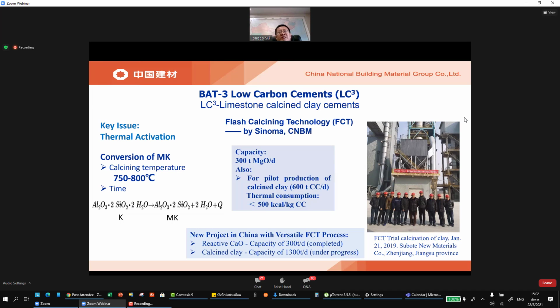And also the thermal consumption of the system is less than 500 kilocalorie per kilo of calcined clay. That's just for the calcination.